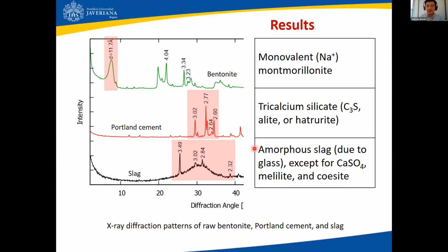And finally, the slag. The slag, for the most part, is amorphous, and that can be evidenced here with this white hump in the X-ray diffraction signal. And that has to do with a lot of glass being present in this material. However, we also found, and you can see here, some peaks that are representative of other materials that have been reported in the literature as well in slags: calcium sulfate, melilite, and coesite, some particular minerals that are present typically in slag materials.